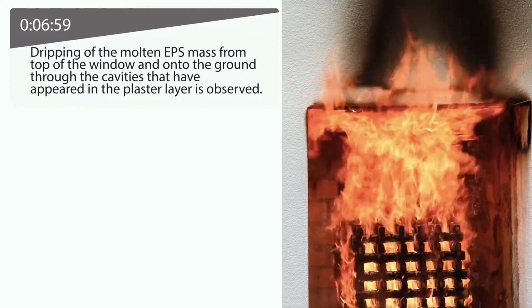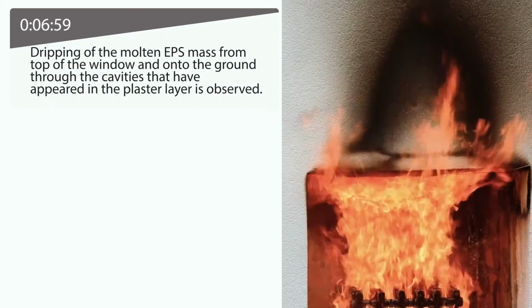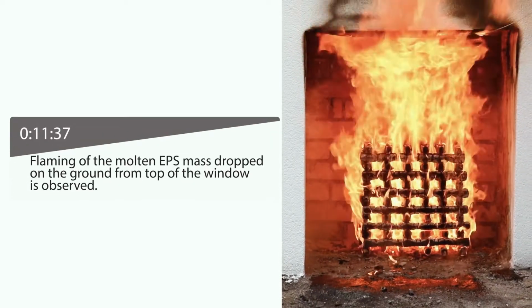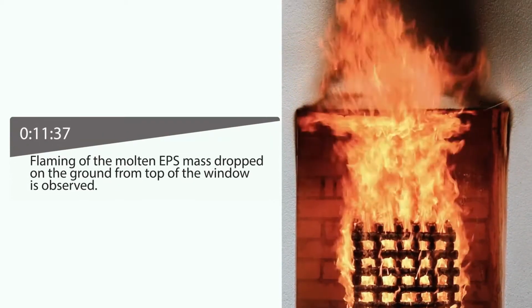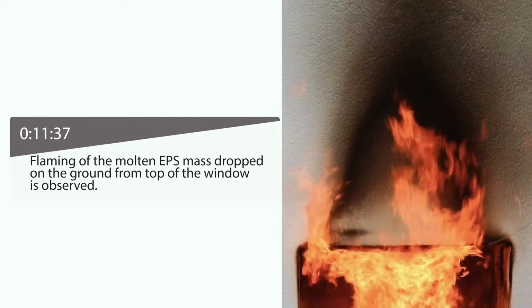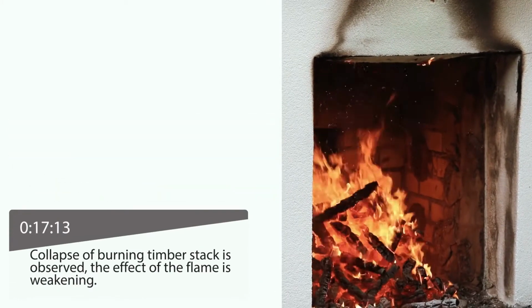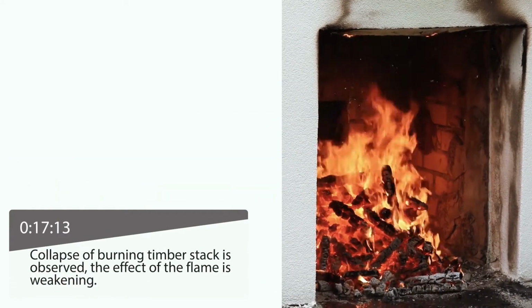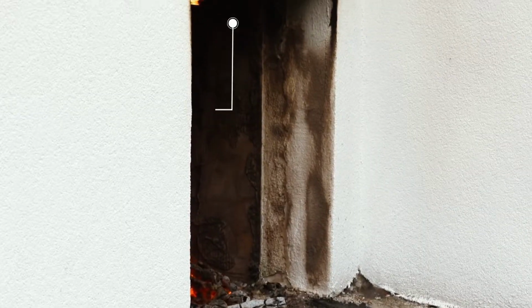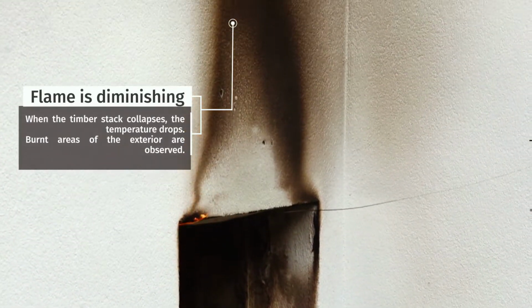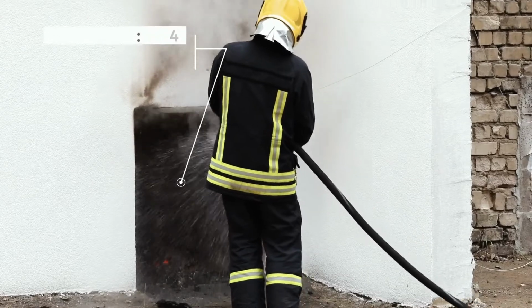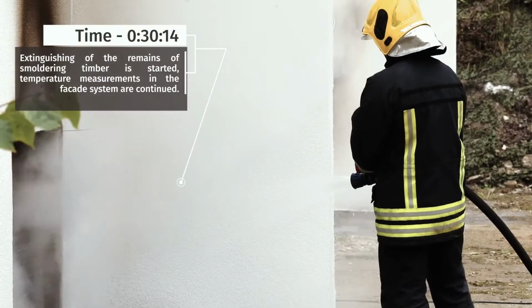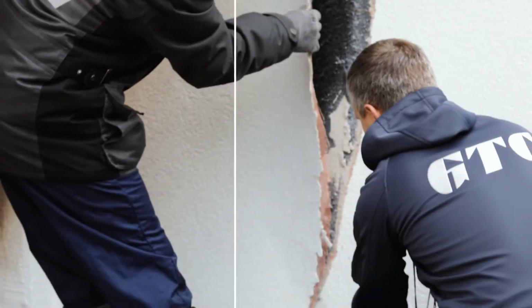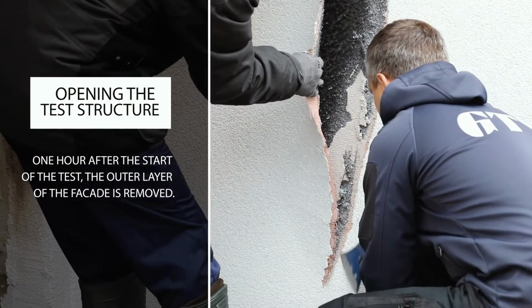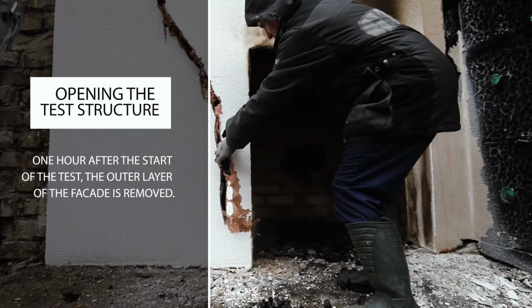Almost 7 minutes after the start of the test, dropping of molten EPS from the top of the window is observed. After more than 11 minutes, flaming of mass of melted and dropped EPS is observed. After 17 minutes, the collapse of the timber stack is observed. When the timber stack collapses, the temperature drops. After 30 minutes, extinguishing of the remains of the timber is started. 1 hour after the start of the test, the outer layer of the facade is removed.